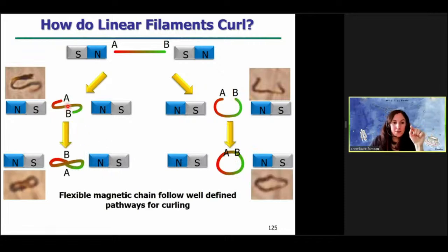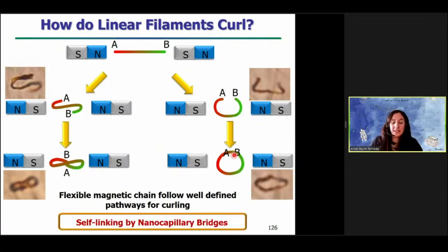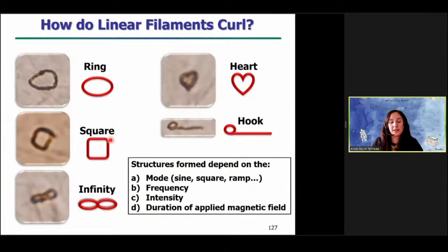And when the two ends meet at the middle of the filament, when they touch each other, they just stick to each other due to the capillary bridges and the self-linking properties, and you obtain the formation of an infinity structure. But when the two ends meet each other like this, they form kind of rings or square structures. And this is really due to the self-linking by the nanocapillary bridges. And so we observe at the end some rings or some squares, depending on the bending modulus of our filaments, some infinity structures, or sometimes some heart or even hook. And the structure really depends on the mode, the frequency, intensity, and duration of the applied magnetic field.